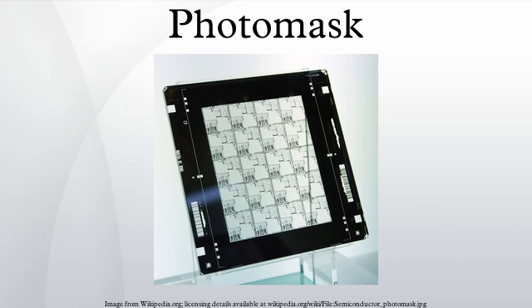exposure is achieved. Features 150 nanometers or below in size generally require phase shifting to enhance the image quality to acceptable values. This can be achieved in many ways. The two most common methods are to use an attenuated phase-shifting background film on the mask to increase the contrast of small intensity peaks, or to etch the exposed quartz so that the edge between the etched and unetched areas can be used to image nearly zero intensity. In the second case, unwanted edges would need to be trimmed out with another exposure.